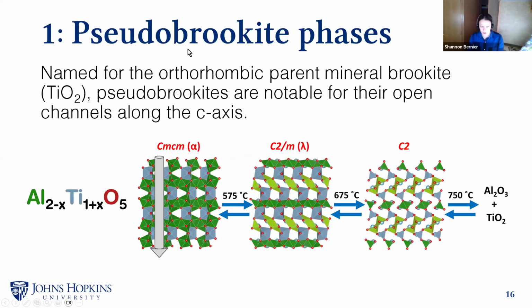So jumping in with the first one, pseudobrookites are a materials family that was studied previously by our postdoc Davor. They're all related to a mineral called brookite. They're all orthorhombic, and that's how they're similar to this mineral. And they're notable for a couple of reasons, one of which is that they have these open channels along the C-axis. This can make them interesting for battery applications because you can put things into those channels. They also have really interesting anisotropic lattice expansion properties, which can be very important. And if you've got magnetic atoms, they can also have interesting magnetic properties.